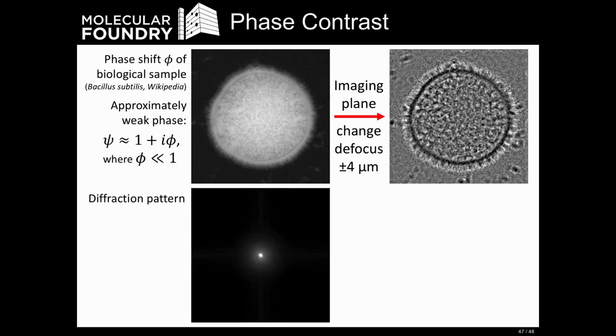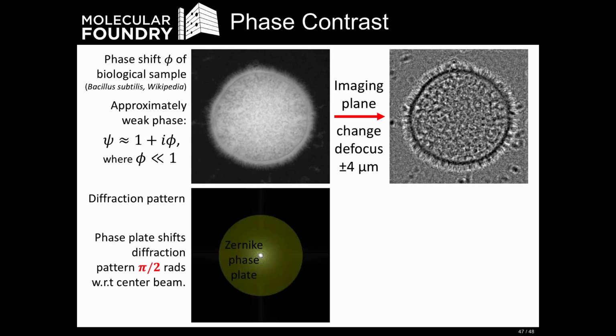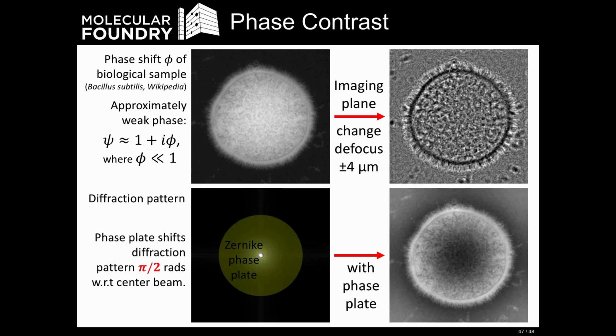Alternatively, some of you might be familiar with another way to see phase contrast images. If I look at the diffraction pattern of the signal just by taking the Fourier transform, and I were to place a Zernike phase plate over top of it, if I phase shift the entire diffraction pattern by pi over 2 radians with respect to the center beam, so I leave the center beam alone, I just phase shift all the diffracted pixels, I form an image like the one on the right. And so that's another alternative way of turning invisible phase contrast into intensity contrast.